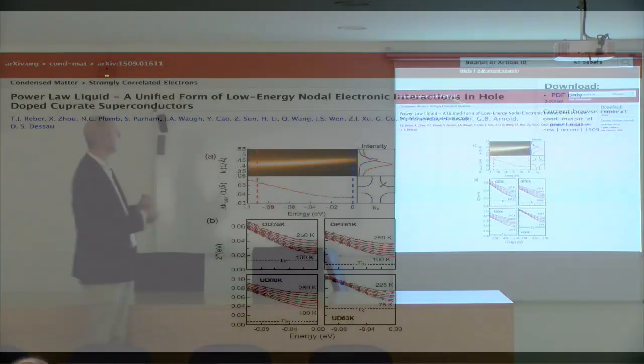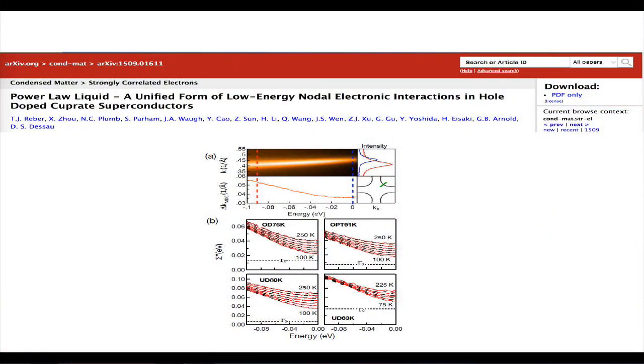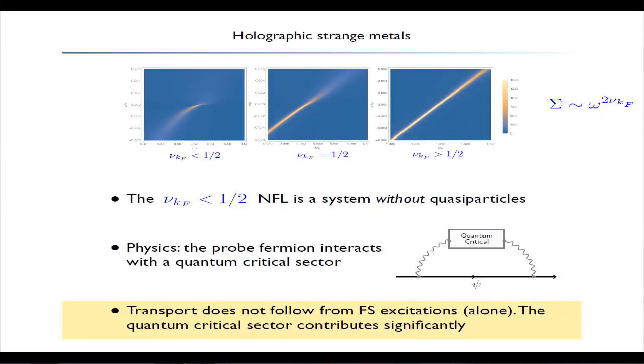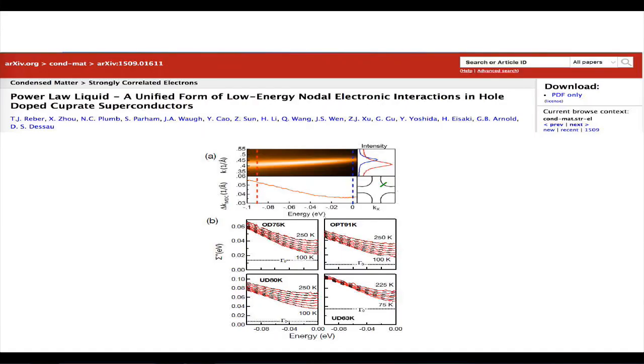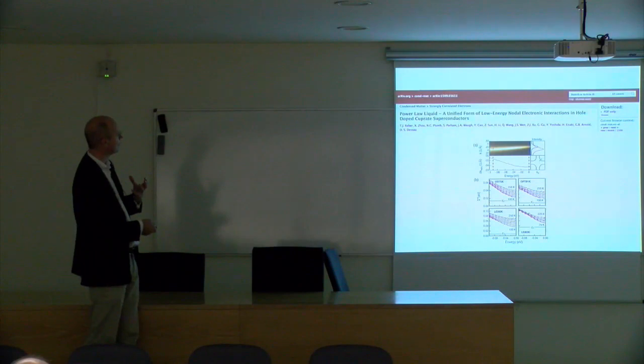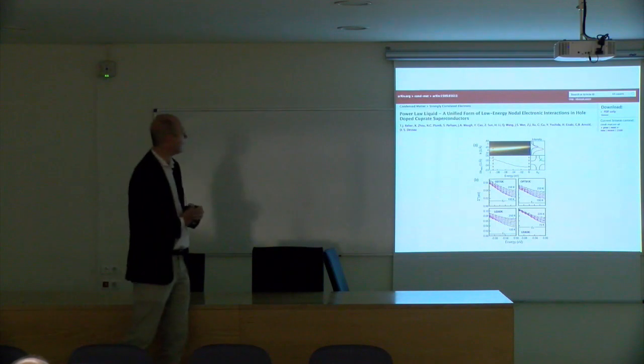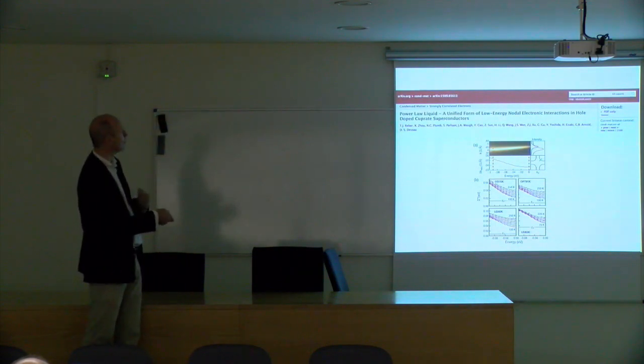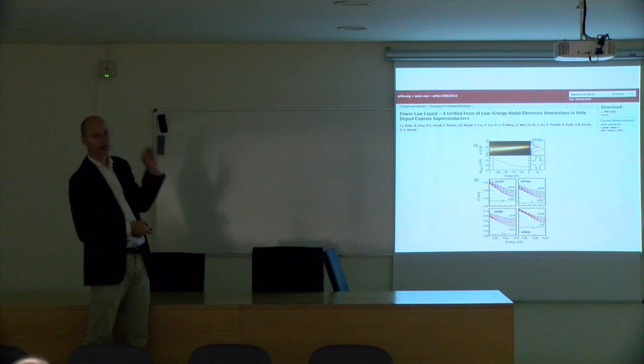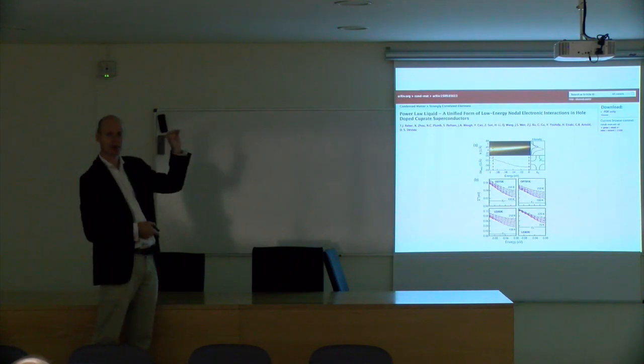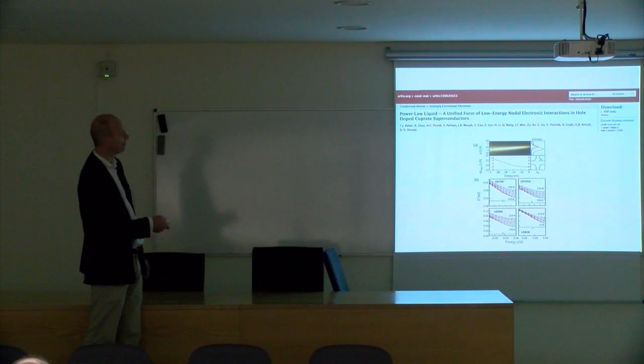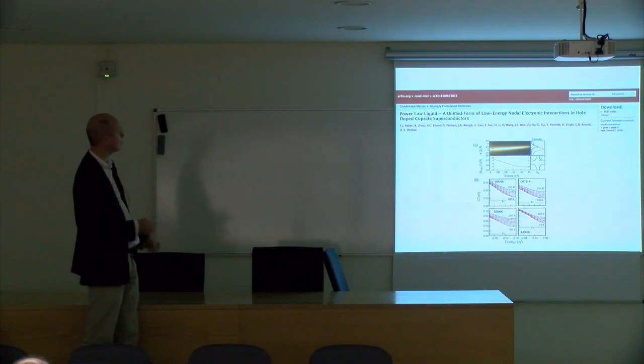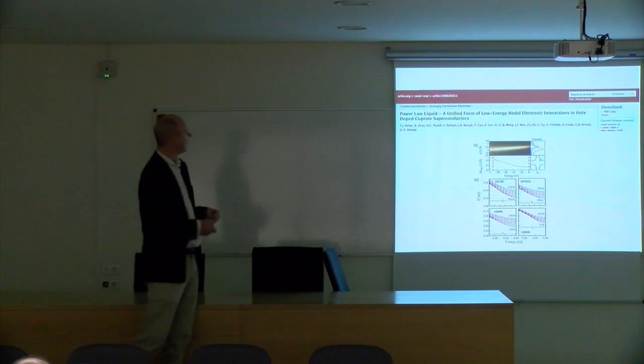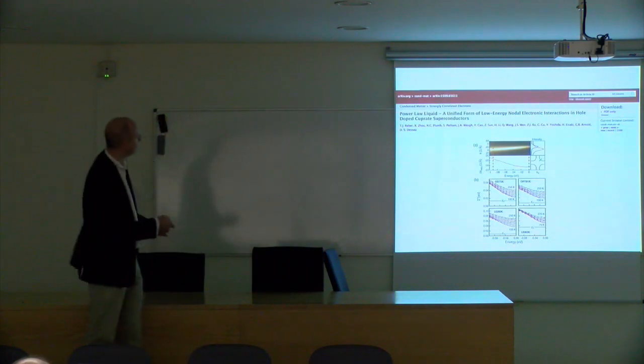Now, what was so exciting is that this was computed in 2009, 2010, and in 2015, there was a group in Boulder, Colorado, led by Dan Dessau, who actually, in a high-precision ARPES measurement, measured precisely the self-energy. Here, this is the imaginary part. Here you see it's the same symbol. And here you see, for various different samples, the OD means this is an overdoped sample. That means that you have put so many holes in it that the superconducting temperature goes down again. This is optimally doped. That's when the temperature is the highest. And this is underdoped. So three different samples.